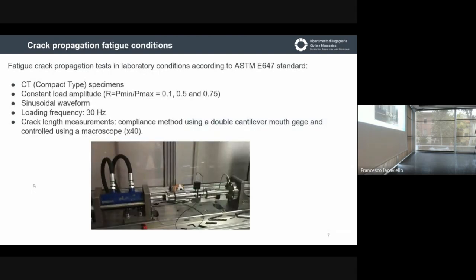So, what is the behavior in terms of crack formation? We use three different load ratios, 0.1, 0.5, and 0.75, in order to understand the behavior when changing this parameter. The frequency is 30 Hertz. Then we calculate the crack length using the compliance method, and this value has been controlled by a microscope. The microscope is here, and the camera is there.